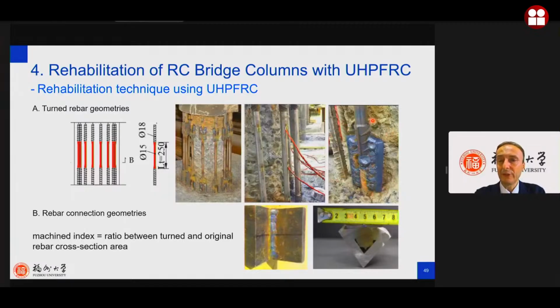So you can see here the connection. This kind of connection was selected after comparing many other solutions using mechanical connectors or welding connectors. We selected this one because when you put new steel rebars where you already have rebars, you can have, I hope you see from the camera, a problem with the alignment of the existing reinforcement with the new one. So to solve this geometrical tolerance, we consider that these kinds of connectors can be very good.